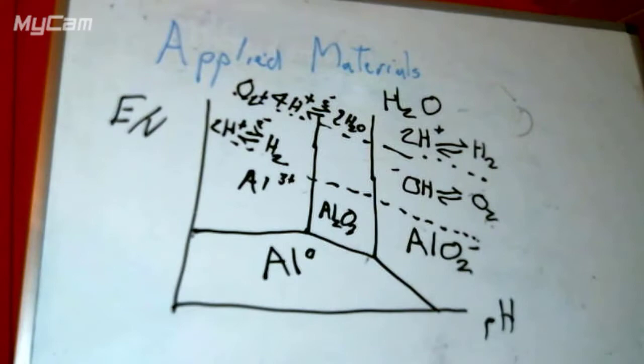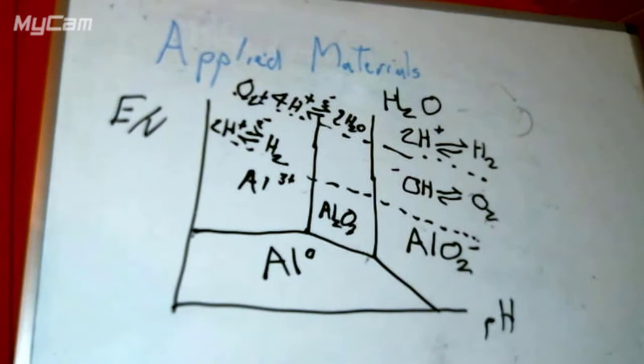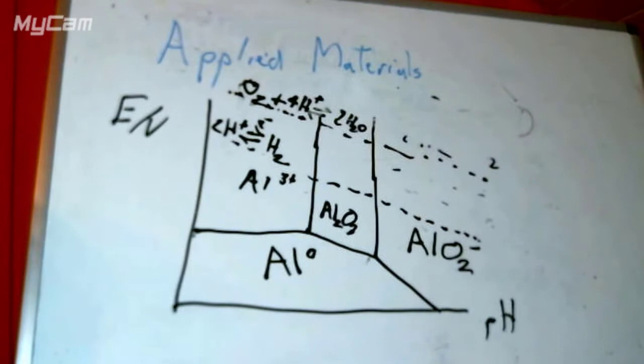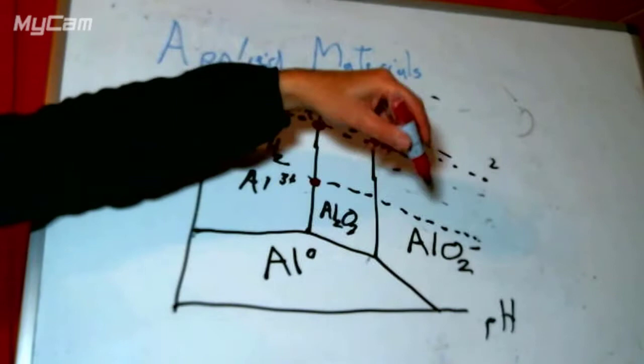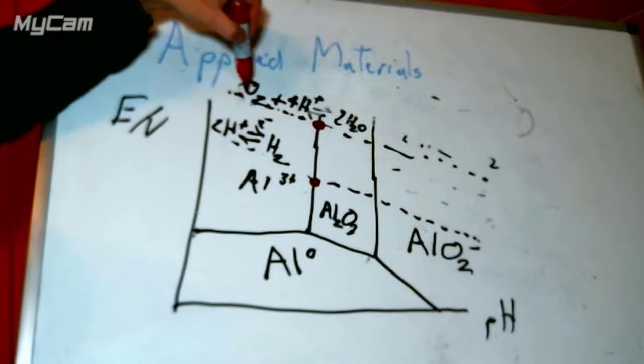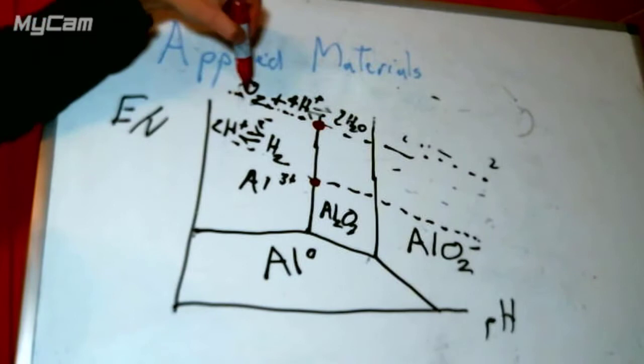One useful thing is that vertical movement can occur with chemistry. If we take two points on the diagram, we can move around — removing dissolved oxygen, for example by bubbling nitrogen through our water, moves us from the upper oxygen line down to the lower hydrogen line. If we remove the dissolved oxygen, effectively the oxygen reduction reaction can't occur, and we allow the water to be stable unless we electrolyze it into oxygen and hydrogen.